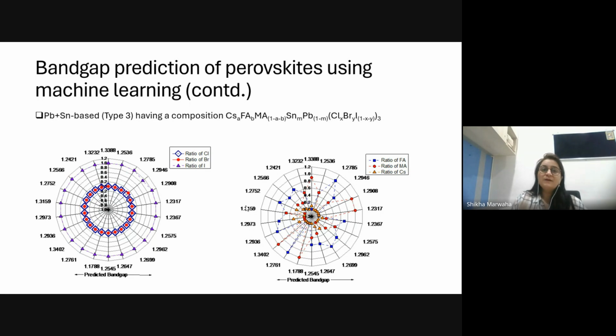But can we do something about this, so that we can mix lead and tin? In this combination, the cation and the halide were the same, but here again we varied tin and lead. A few combinations of lead and tin were included, in which we can increase the tin coefficient and use a minimum value of lead, and then see the impact on the band gap. Because it's not the band gap that ultimately determines the efficiency of my material; I need to look at the stability. If I'm looking at commercial purposes, there are many other factors that need to be considered.